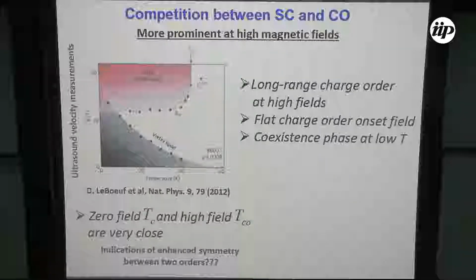Interestingly, if you look at this onset field, this is quite flat with temperature. That means it does not depend on temperature up to a very significant amount of temperature. Second feature, what we can see is that at low temperature, there is a coexistence phase between superconductivity and charge order. There is a third very interesting feature: if you look at the high field charge order transition temperature, TCO,